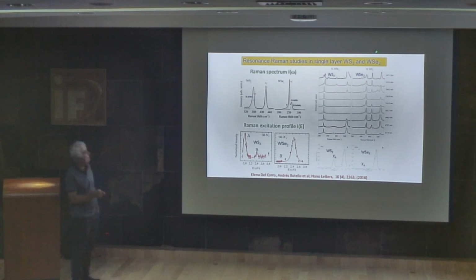And we did a similar experiment now with tungsten disulfide and tungsten diselenide. They're very similar compounds. And this is the Raman spectrum of tungsten disulfide and tungsten diselenide. What we realized here is that, for example, in the case of tungsten disulfide, we have the enhancement of this totally symmetric mode with the A and B exciton, and it was a very normal behavior. But in the case of tungsten diselenide, we could not see the enhancement with the B exciton.